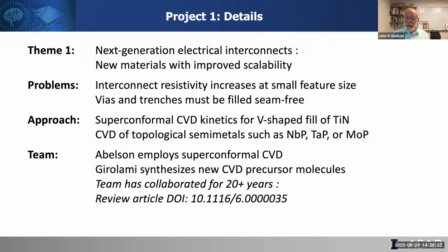If one imagines a deep via or trench with parallel sidewalls, conformal growth can coat these walls. The difficulty is that as the coating becomes thicker and thicker, the walls grow inwards until finally, inevitably, there's a seam of material in the middle which is not filled. And this is a problem because it's subject to high etch rates during CMP and other steps. So a process like atomic layer deposition is beautiful, we all know, but it's conformal. So it too leaves a seam in the center.